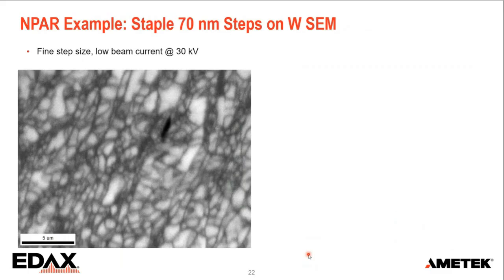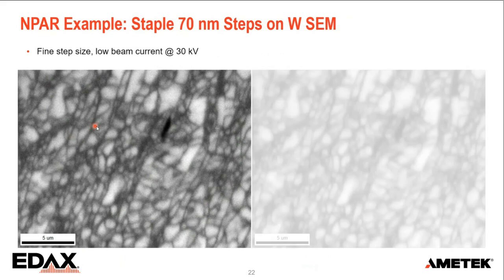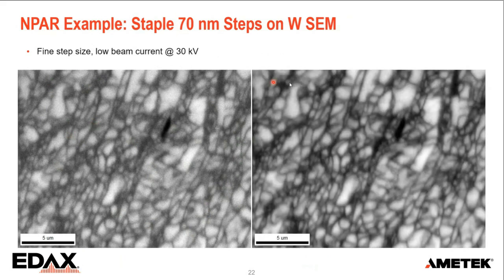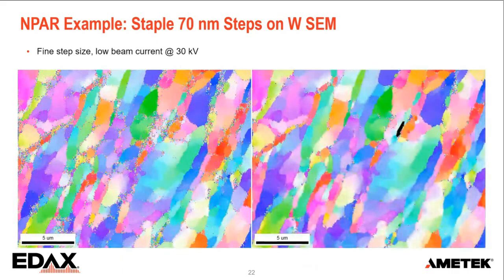And just to illustrate what that looks like, here I have a sample with a very fine step size and small beam current. So you get a bit of a noisy map, you get bad indexing along grain boundaries. When I go for NPAR on that, the signal-to-noise ratio improves dramatically. You can see all the small structures here that were just lost in the noise in this one. And also the indexing improves from about, what is it here, 80% to maybe 99%.